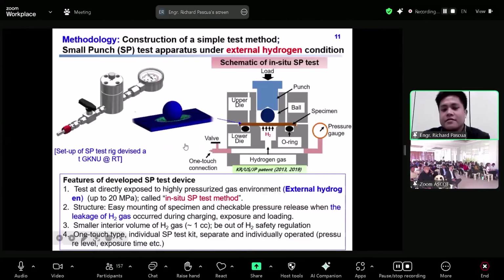And this is the construction of our simple test method developed at our university, in which the specimen is located between the upper and lower die, and we utilize a steel ball to punch the specimen while exposing it to the high pressure hydrogen environment using the puncher. We utilize a pressure gauge to monitor the pressure of the gas during the test. And this is how the material deformed after applying the load.